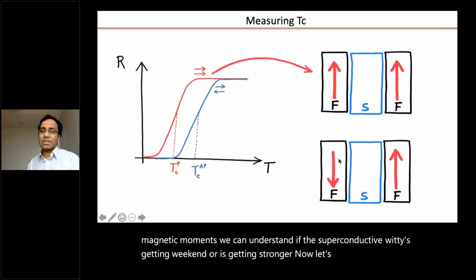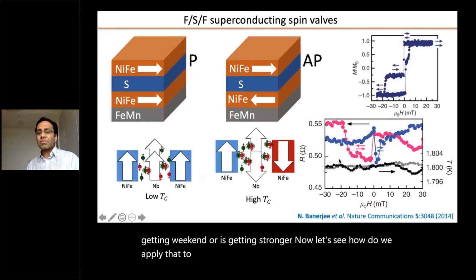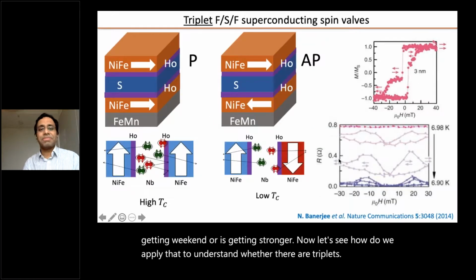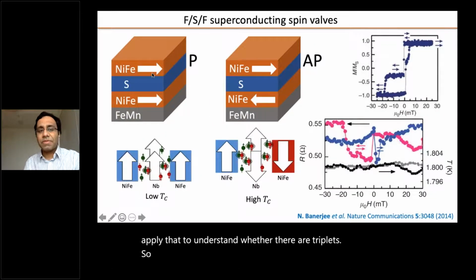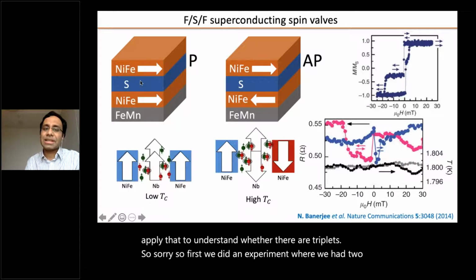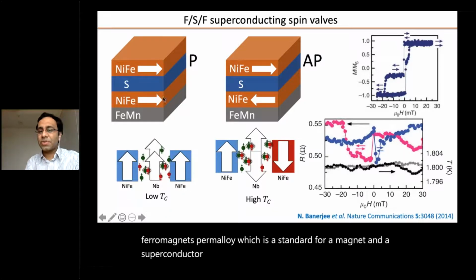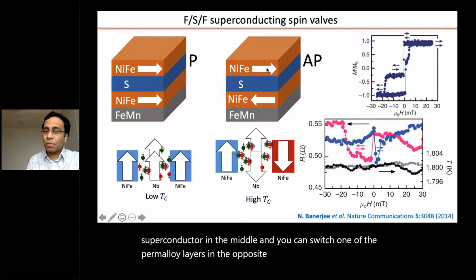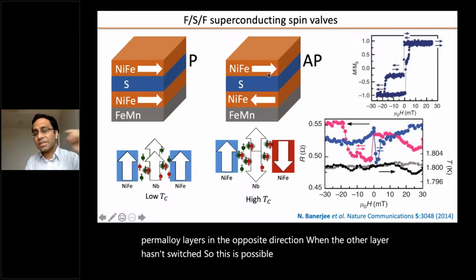Now let's see how we apply that to understand whether there are triplets. First, we did an experiment where we had two ferromagnets, permalloy, which is a standard ferromagnet, and the superconductor in the middle, and you can switch one of the permalloy layers in the opposite direction when the other layer hasn't switched. This is possible by something called the exchange bias. I'm not going into the details of that.